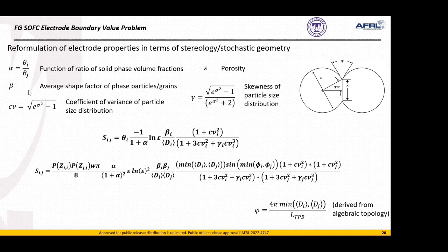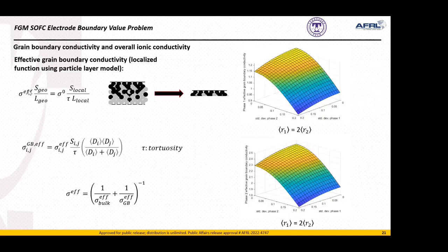In addition to that, we have also defined a novel relation here for the interfacial surface area between particles of two separate phases. Again, using notions of stochastic geometry and deriving some of these relations from algebraic topology, where we can see that the dihedral angle, the length of contact between grains, is related to our triple phase boundary definition as well. Now, where all of this is important is in defining effective geometric grain boundary conductivity and the overall conductivity of the electrode.